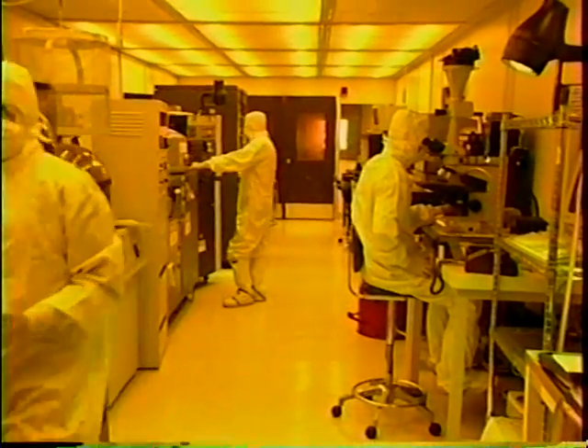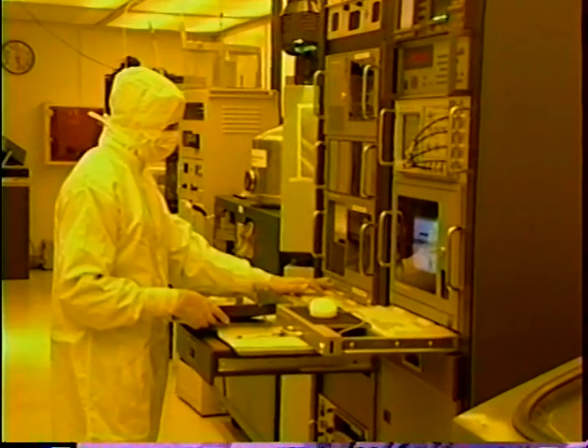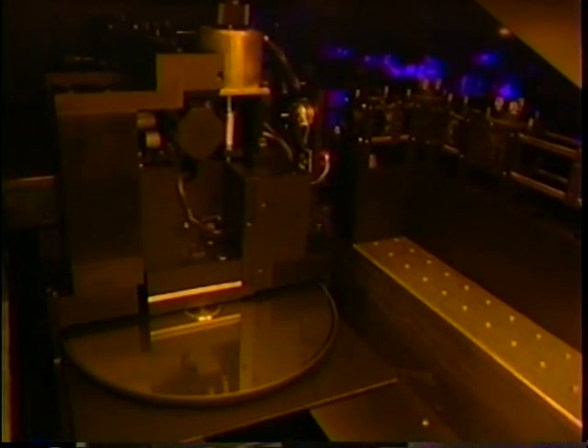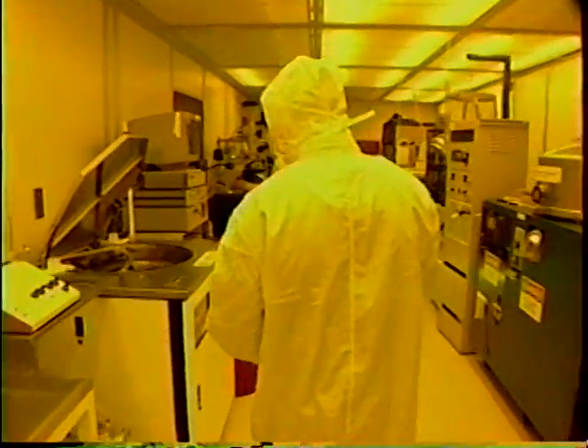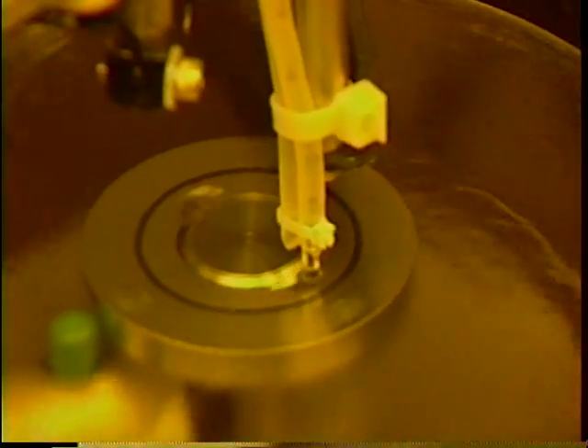When a master is about to be made, the customer's digital source material is retrieved from our limited access vault to be sent onto the laser mastering room, where it will be recorded onto the glass plate. It's on these mastering machines that data from the digital tape will be fed to the lasers to create the microscopic pits and lands. The glass is placed on the mastering table, where it is slowly positioned to spin under the laser beam. The laser travels through precision optics and is focused onto the spinning glass. The data on the customer's tape modulates the laser, turning it on and off nearly two million times per second, exposing the photosensitive material wherever the laser shines. The exposed glass is then removed to be developed like film — in this case the exposed parts are washed away, leaving the microscopic pits that now represent the information.